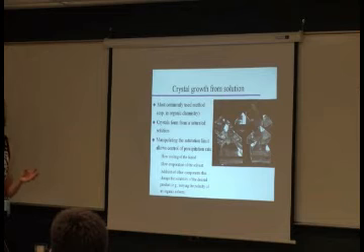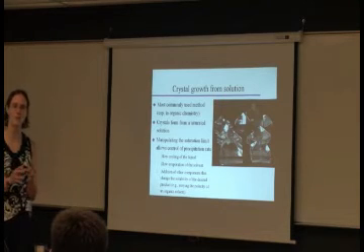So, this is grown by what is the most commonly used method, at least in organic chemistry, from solution. What they did was they manipulated the saturation limit, because that is what determines your nucleation versus growth. What you really want is a saturated solution that you slowly cool. So you just hit that area where it is super saturated. So things want to crystallize out. But if you don't have a lot of nucleation sites, you form very few nuclei. And then you start depositing materials on these nuclei because they are kind of impurities, right? They are crystallization sites. They are a place where it is easier to deposit material.